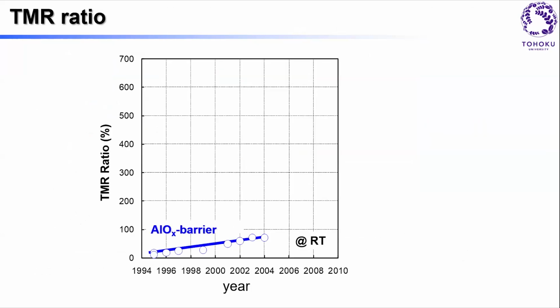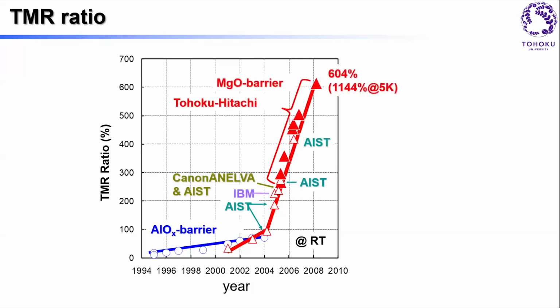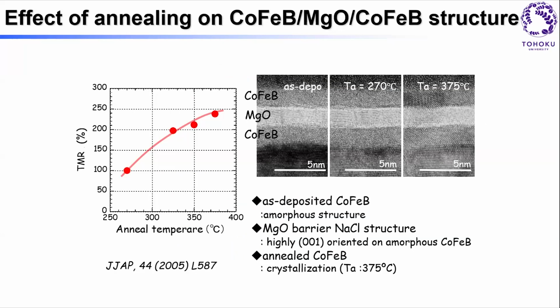So basically, with this crystalline structure, you can make iron as if it is 100% spin polarized. And well, experimentalists, of course, took it seriously and went on to see whether we can realize this promise. And indeed, remember that we only had 70% with the ordinary incoherent tunneling scheme. Now we can go up to 600% or even more. Okay, and by using cobalt iron boron, MgO, plus annealing, we got very lucky in a sense. Mother Nature is not always mean in that regard, because here,